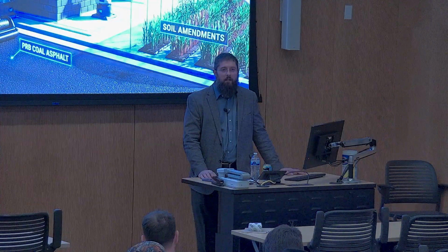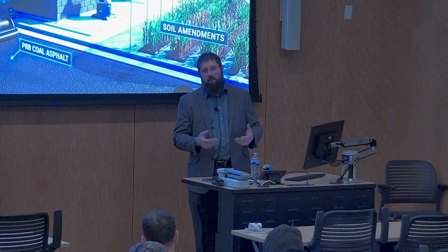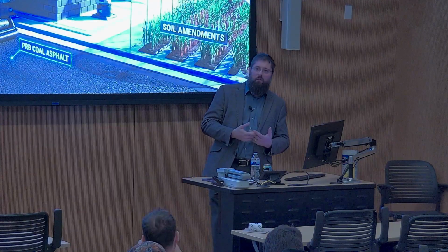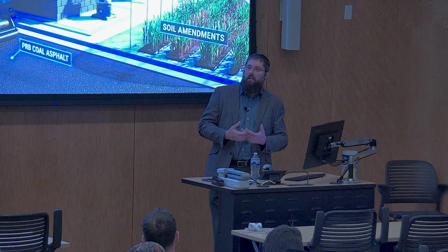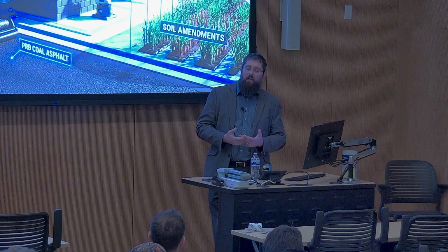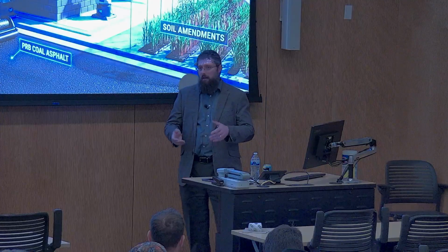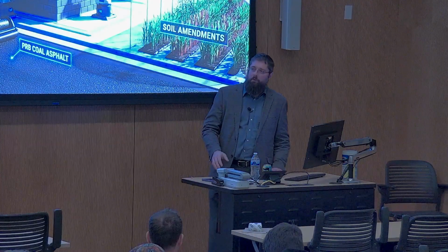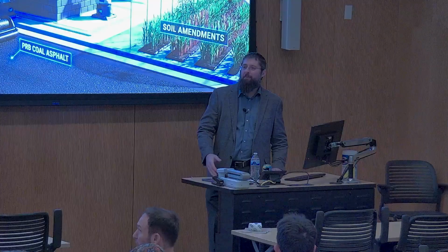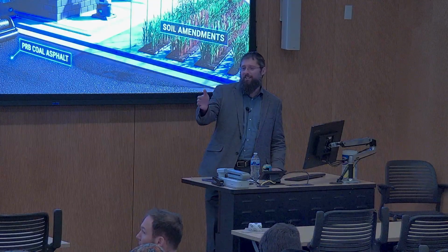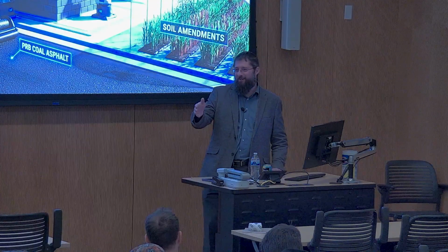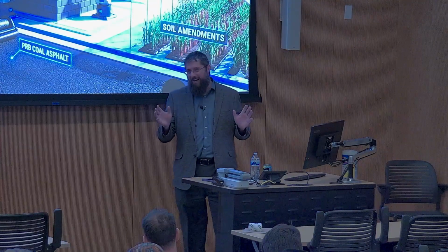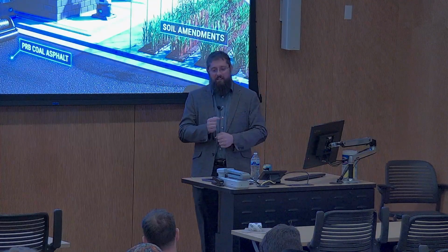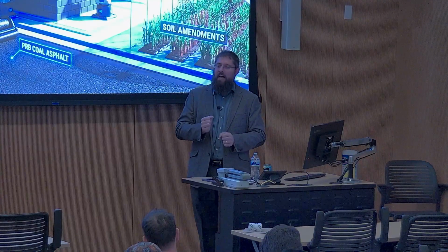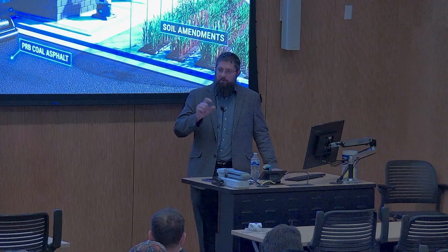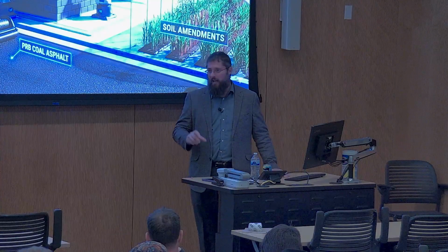Yeah, so there's the cohesion, the strength of the material, which is how well it's going to hold together internally. And there, in the paving world, we do have a test to do that. It's called the multiple stress creep and recovery test. Thanks, Yogesh. Yogesh is a civil engineer on our team, and he deals with the rheology. I'm the chemist, so I'm a little bit dumb with the rheology. But this is a test where you stress it, then you let it relax, and then you do it again and again. There are some thresholds that you can use to weed out materials that have bad cohesive strength.